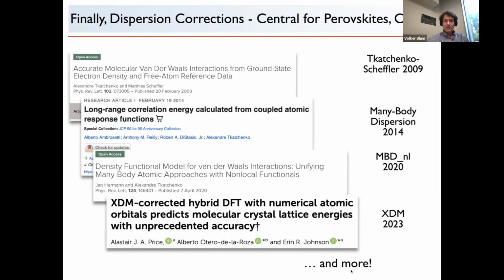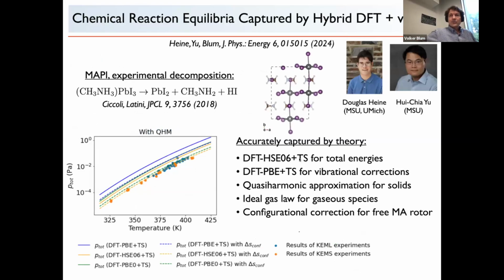And so this is growing, and this enables us to do calculations that capture both the short range accurately in terms of hybrid DFT and the long range dispersion interactions for these weakly bonded systems, where the weak bonding, however, is important. We can use this. So this is a hybrid perovskite, and this is an undergraduate student, Douglas Heine, who is now at the University of Michigan, who did the bulk of this work.